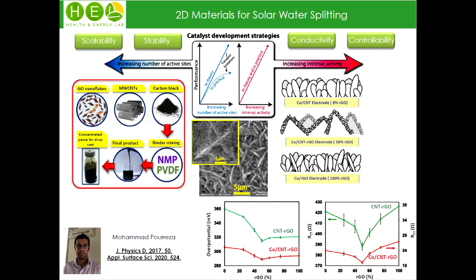As I mentioned, we have two strategies for providing more efficient catalysts. One is increasing the intrinsic activity of the catalytic site, the other is increasing the number of active sites. In the latter, it's important to produce a surface where transport limitations can be suppressed, and the maximum number of active sites are accessible for the electrolyte. In this context, it's important to have a tunable and controllable method for producing the electrocatalysts, especially at higher scales, because scalability is another concern.